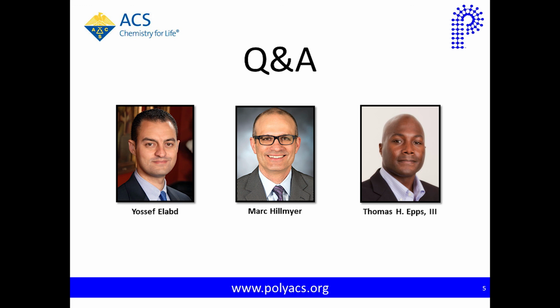And so what that does is, let's not forget that polystyrene is a very hard or more brittle, high Tg material, and it's now connected to that soft material. So essentially the width of that interface, or the strength of the interaction between the PS and PEO, influences that PEO chain motion. So that's one of the things that we found in the tapered materials, is that by tuning the interfacial width, we're actually able to tune the glass transition temperature. So the link between chi and morphology and glass transition temperature, ultimately leading to transport, is a very important one. Absolutely. Yes, thank you, Thomas.